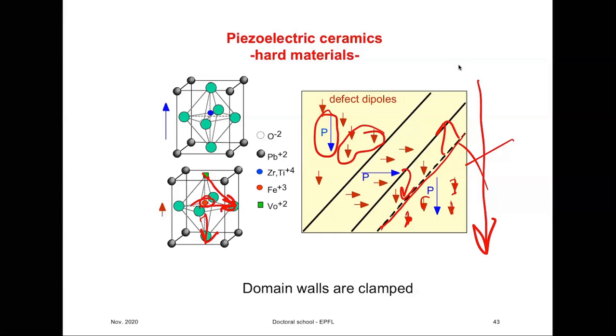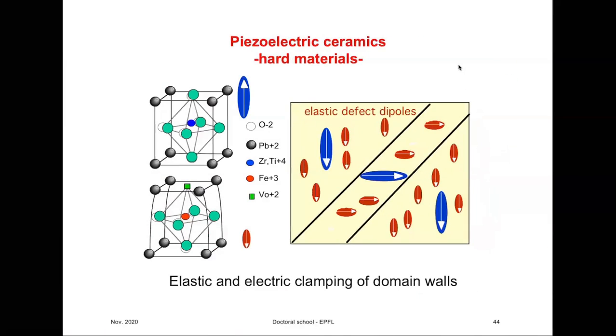Now, if you apply very large field, then you will move both defect dipoles and spontaneous ferroelectric polarization. There is another factor here, and that is that around this oxygen vacancy, the lattice will be distorted. And it can be distorted two ways. If oxygen is missing here, then there is no negative potential of the oxygen atom between these positive lead atoms, and they can be either repelled, or because we have one ion that is missing there, the lattice can actually become smaller there. And the different oxide materials will behave differently. So I actually don't know.